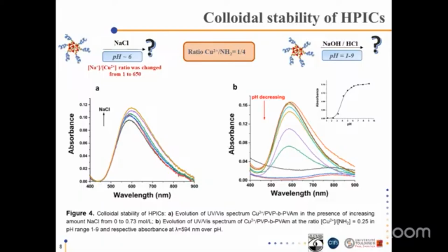Lowering the pH down to 4 led to a significant decrease of measured absorbance. Below pH 4, the absorbance sharply decreases, and UV-visible spectra show only a weak band around 800 nanometers corresponding to free hydrated copper ions. These results confirm that the interaction between copper ions and amine groups is the driving force behind HPICs' assembly.